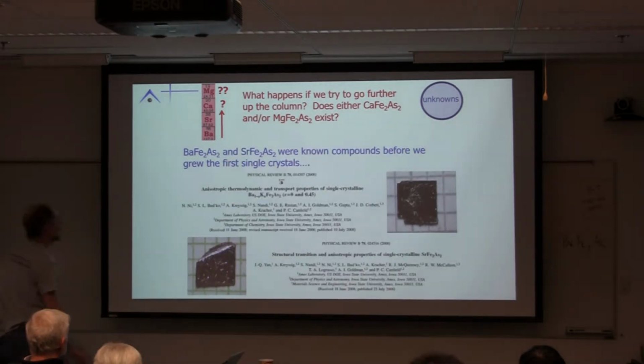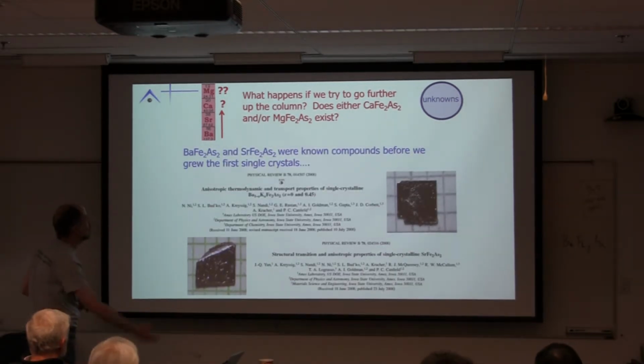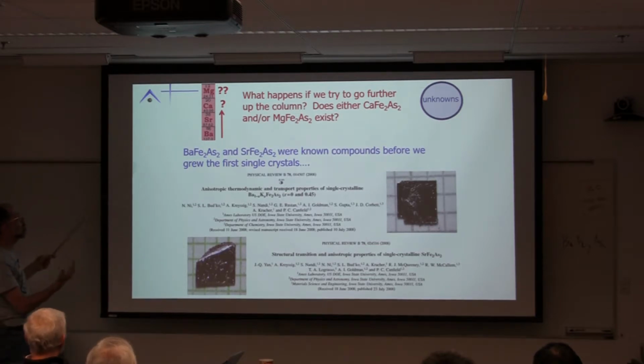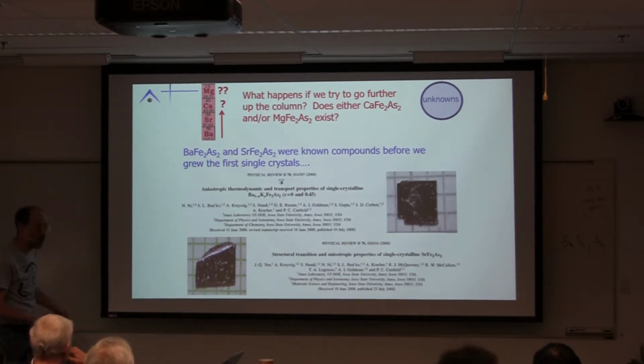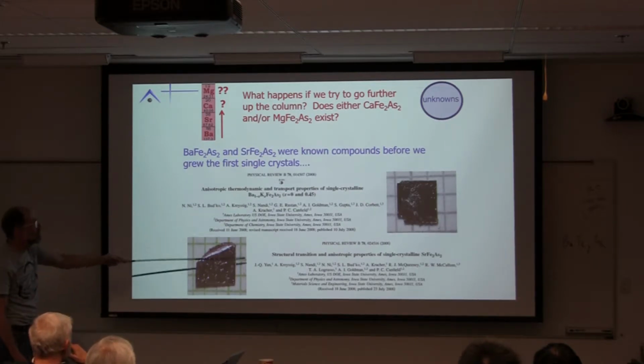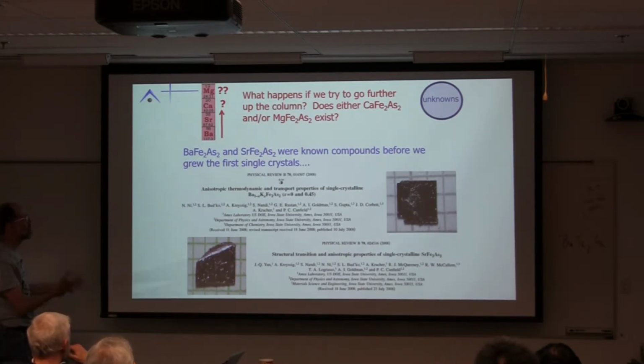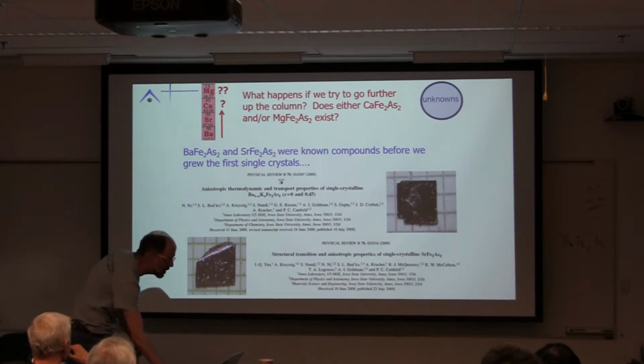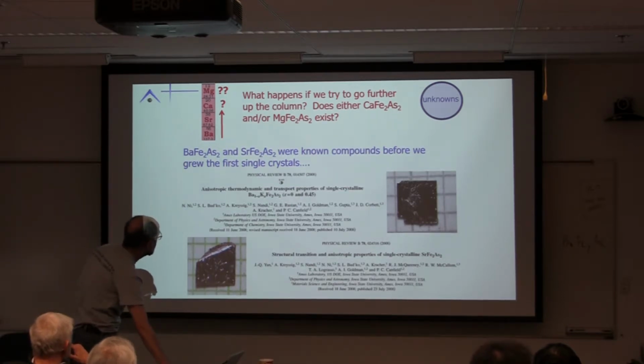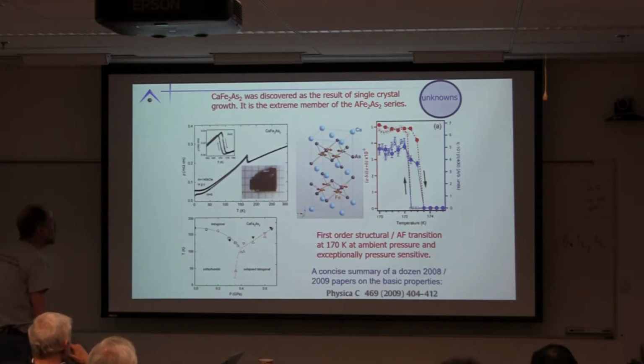And the reason I say this is barium and strontium iron two arsenic two were known compounds before the first crystals were grown. These were materials that were in the structural literature, they were known, and basically the realization was you can actually dope these and get these to superconduct. But they were known materials. On the other hand, calcium iron two arsenic two was not a known compound. But at this point, obviously, we'd like to see, and this is a rare example of actually growing a new material first in single crystal form, in large form.